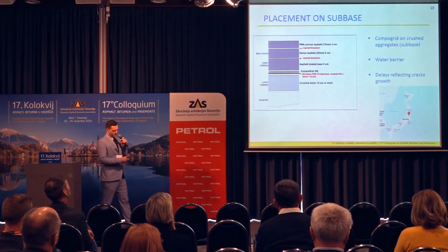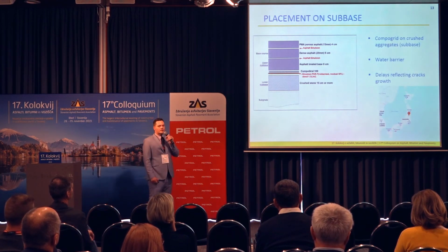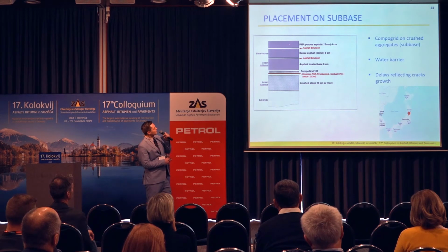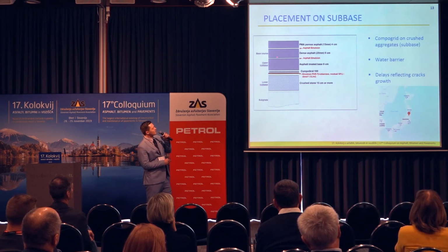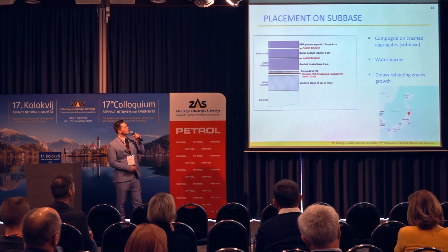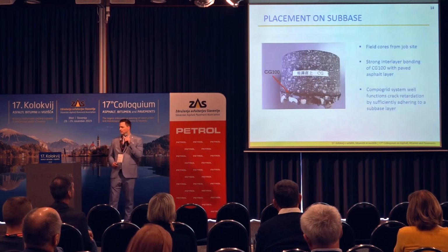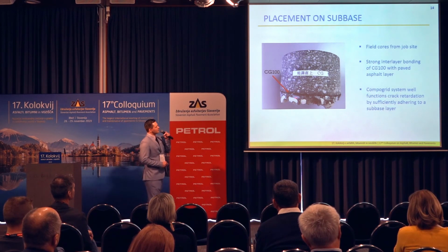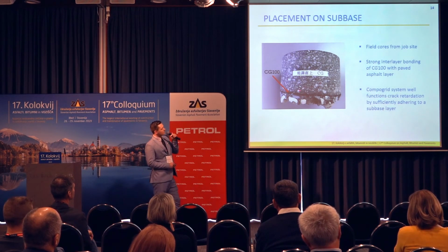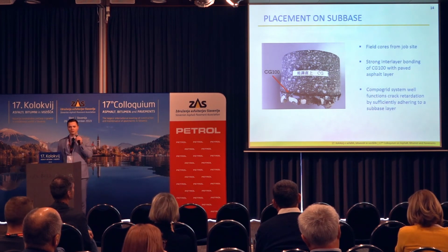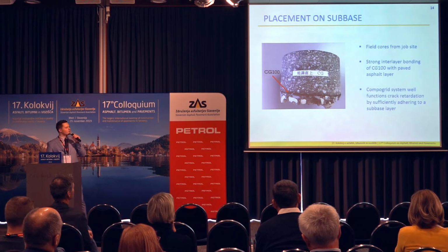So the project we did was in Japan. And normally, as I showed you at the beginning, we place the grid under the wearing course or the leveling course. But in this case, we applied the grid right on the subbase, on the crushed aggregates. So here you can see the core from that project. You can see that the bond is very good, which is the key parameter. The adhesion between the layers must be good to activate the function of the reinforcement.